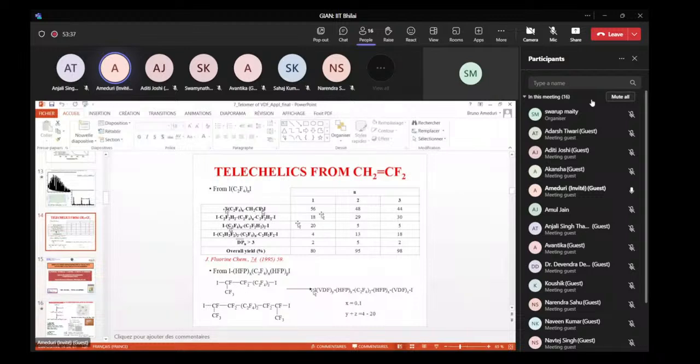I cannot say it's a block copolymer because we have a very low amount of HFP. HFP does not homopolymerize. So, of course, in the first step of telomerization of HFP, it was possible only to have 1 monoadduct or 1 alpha or beta diadduct. So these new telomers of HFP could be used as chain transfer agents for further telomerization of VDF.